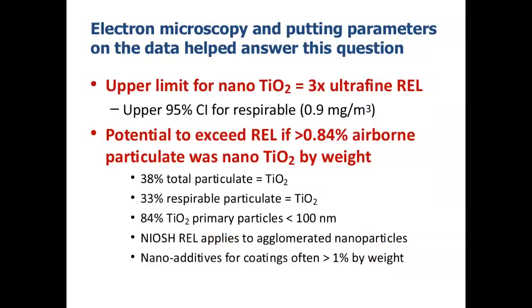So based on the 95% confidence interval for respirable TiO2, we estimated that the upper limit of exposure to nanosized TiO2 while spraying to be three times the NIOSH REL for ultrafine TiO2. So that would be the upper limit based on the respirable estimates. We also calculated that there would be potential to exceed the REL if more than 0.84% of the airborne particulate while spraying was nano TiO2 by weight.